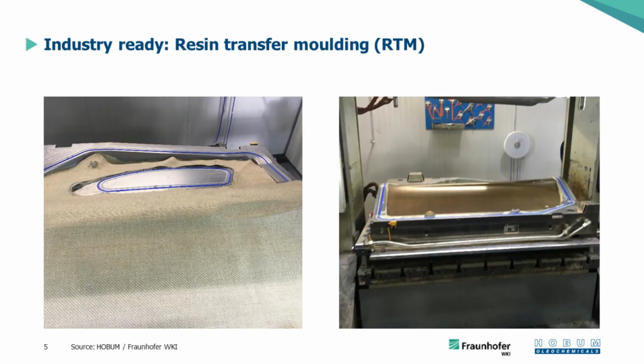How is it done? I will show two main ways to apply it. One is resin transfer molding, where you have a convex and concave mold with a void, and it's a press system, so the upper layer will be pressed on the bottom layer. You put the linen fabric inside, close the two molds, and then pump the A and B mixture into the system and fill the natural fiber product with the resin system. And if you've done it right, you will get the result on the right side.